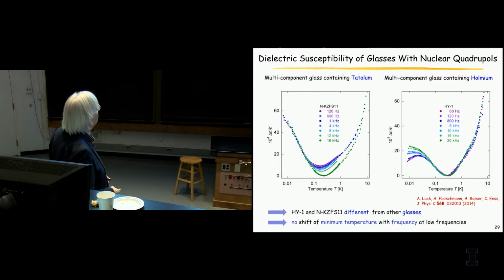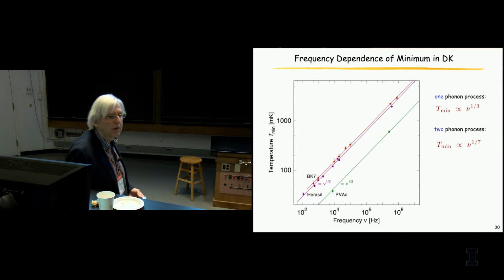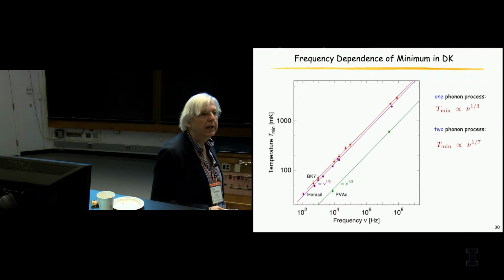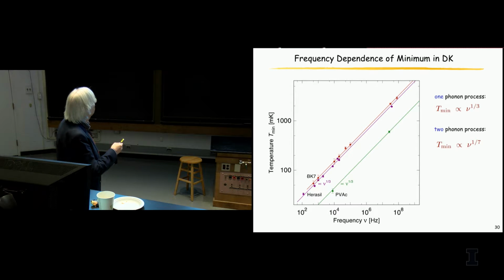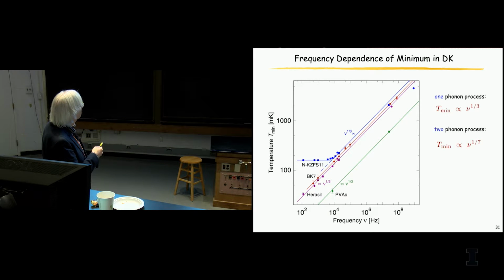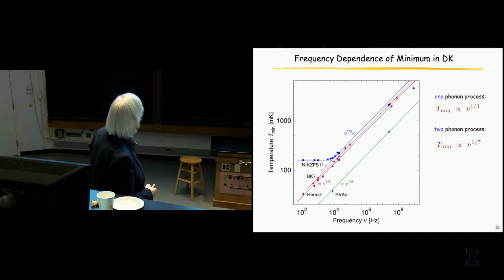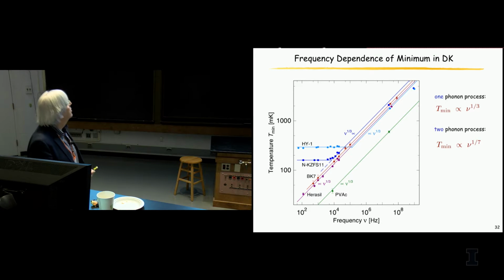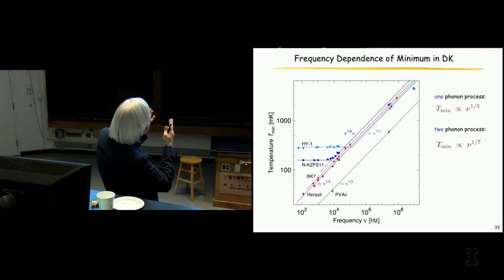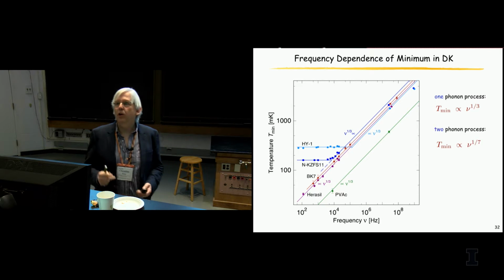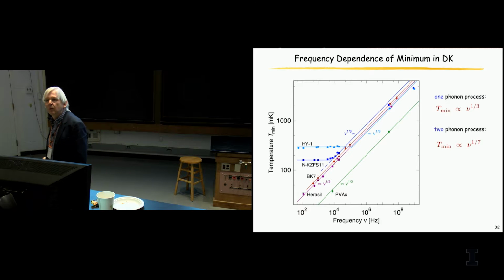And if we go back to our plot here, this is our minimum temperature again as a function of frequency, and we put in our tantalum glass, it stops here, the minimum. But at higher frequencies, I didn't show those data, we measured really up to the gigahertz range, it perfectly follows the one phonon relaxation. And for the holmium, it's even more striking. In this frequency range here, the minimum isn't shifting. So this picture alone tells you one phonon relaxation is not the only answer here.